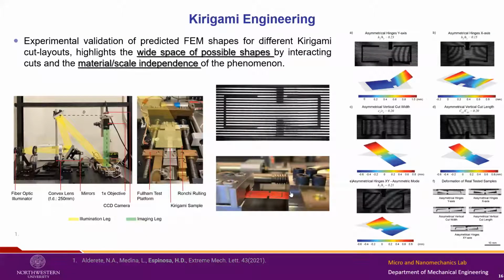And we confirmed these things at the microscale. So we tested some of these patterns at the microscale. We used a very classic, old technique, the shadow moire technique, which allows us to map these out of plane displacements very elegantly. So we were able to confirm these FEM simulations, and show how just small changes in the Kirigami motif, playing with asymmetries and symmetries, we can obtain a very wide range of out of plane shapes.